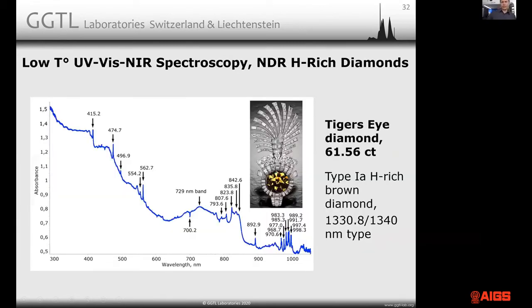Okay, let's have a look at the UV vis. Now this is a really famous stone that shows probably the most beautiful of those UV vis spectra. That's a hydrogen-rich diamond of that 1330.8, 1340 nanometer type. So the one with the near infrared absorption resolved before. And you can see the 900 nanometer peaks that we have seen in the other spectrum and how this spectrum continues. It's a very complex spectrum. It also causes a continuum.